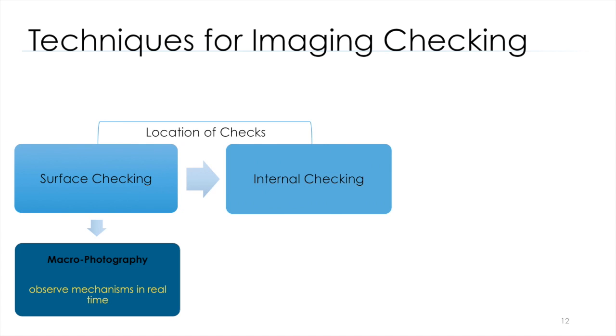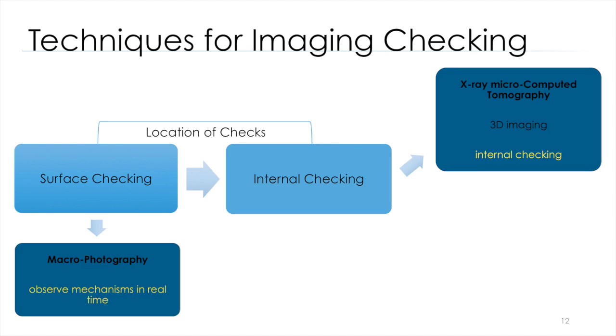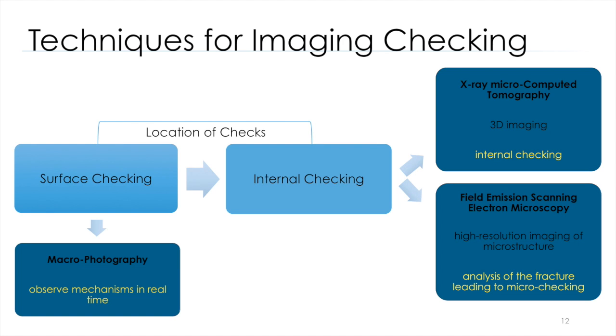Then we used methods that allow us to look at internal checking. So we employed X-ray micro-computed tomography to look at 3D imaging of OSB. Lastly, we used field emission scanning electron microscopy, which gives us high-resolution imagery of the microstructure and enables analysis of the fracture leading to microchecking.